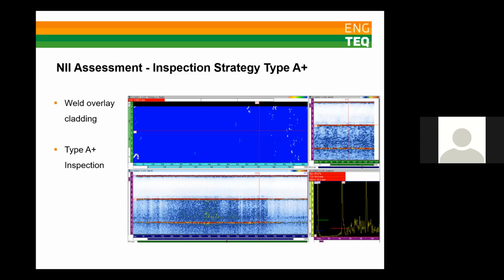And this is what we mean by a type A plus inspection. Where there's a reasonable likelihood of failure of cladding, the inspection should aim to identify any delaminations between the corrosion-resistant alloy cladding and the vessel shell. These can occur immediately after manufacturing, but they can also be caused by surface-induced degradation. And in the case of stress corrosion cracks developing in the cladding, you'd expect them to grow and reach the interface, and it's most likely that they would then cause delamination or disbonding at the interface, since the mechanism for continuation of crack growth in carbon steel would be different to that for the clad material.